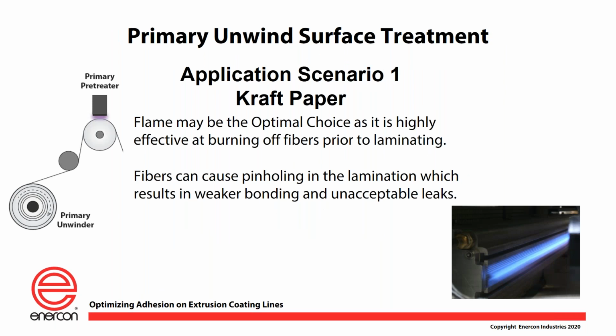So the one scenario that came up is we talked about possibly having a flame treater coming off the primary unwind, especially if you're treating any type of paper, kraft paper, paperboard, etc. Because what you want to do is burn off those fibers so that you get a nice coating as you apply it prior to the extruder, so that you don't have any pinholing and cause any damage to your next process if you don't burn off those fibers properly.